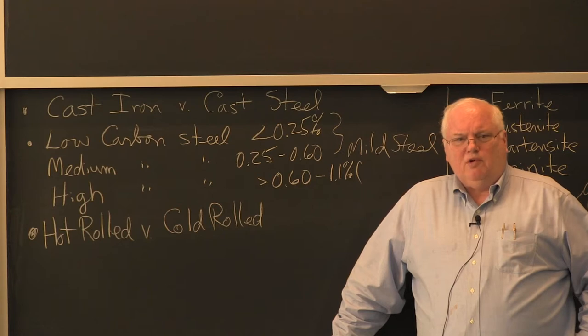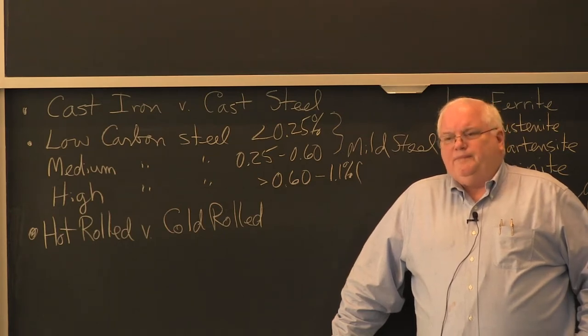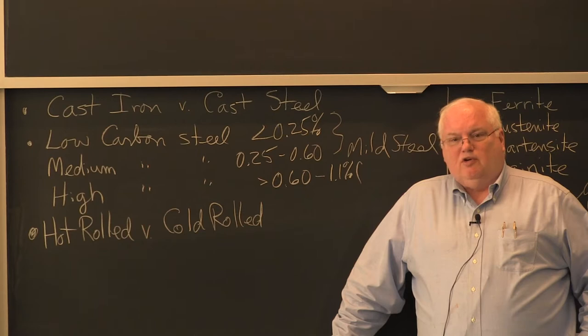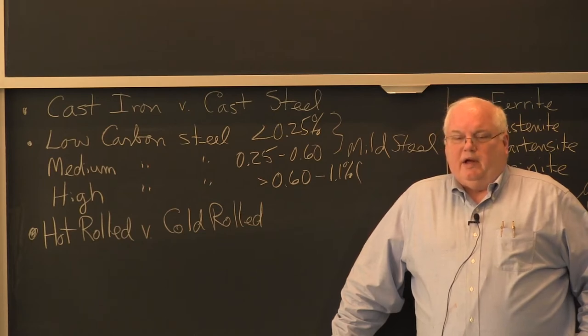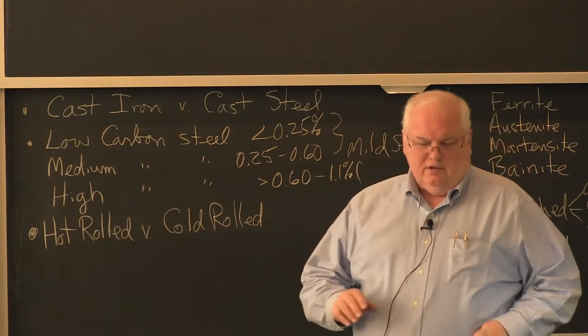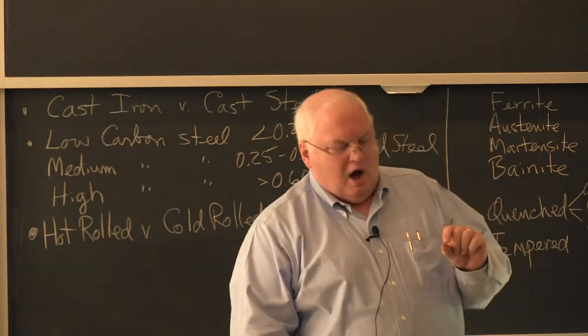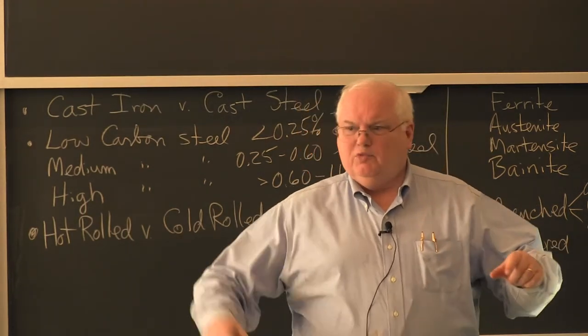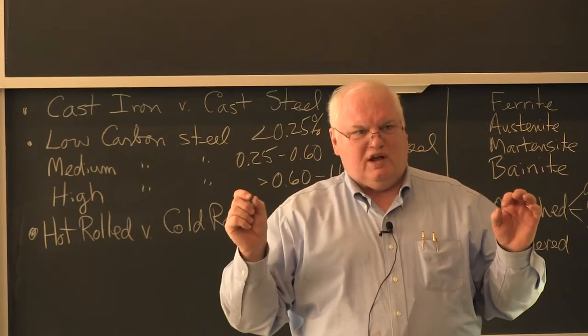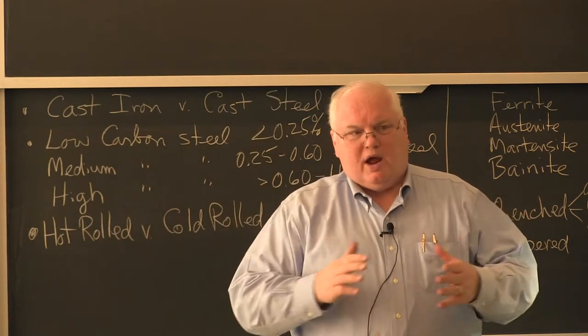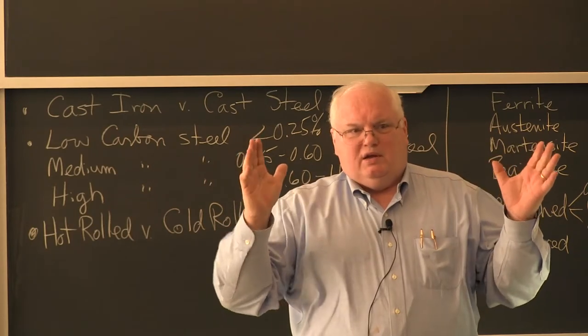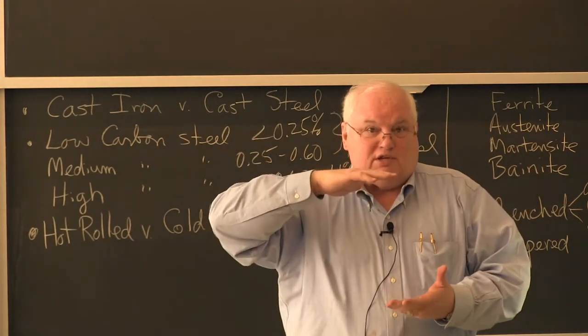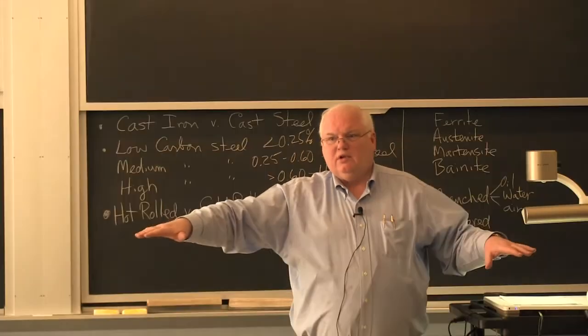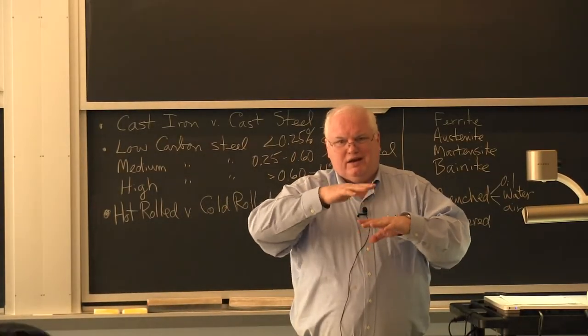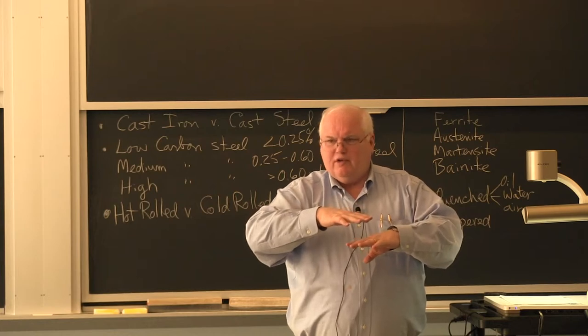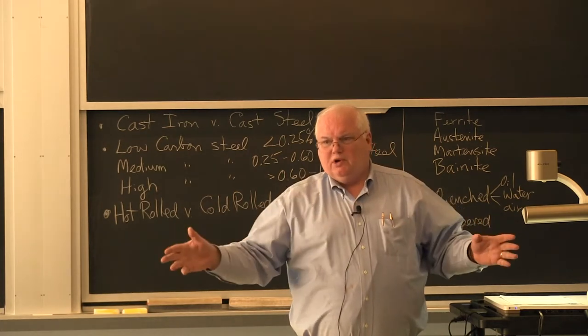Someone else mentioned hot rolled versus cold rolled. And so sometimes you say, well, I have a piece of cold rolled steel. Well, what does that mean? Well, it means it came from a particular mill that can take hot rolled band, they call it, which is just a great big roll of like quarter inch thick steel. Well, let me back up. Steel is made by casting, in the old days, like 20 inch thick ingots and rolling them out. It's basically they call breakdown rolling, and you forge it down to about 4 or 5 inches thick, and then you go through a hot mill.